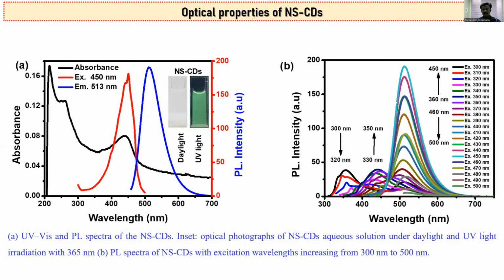The next one is photoluminescence spectroscopy. The carbon dots in aqueous solution, also confirmed by UV spectroscopy, give the same resulting solution. We have to optimize the carbon dots, which exhibited excitation dependent behavior. Previously, I explained this behavior. You know very well, 300 to 320 is the first one. The black line is 300 nanometer, and the blue line is 320 nanometer. It decreases the photoluminescence intensities, and then 330 to 350 gives more enhancement.